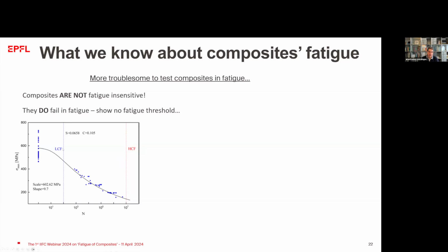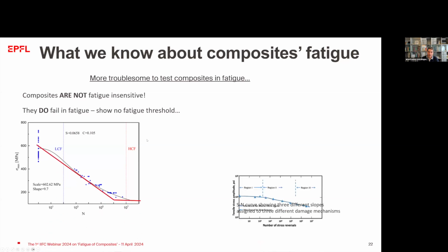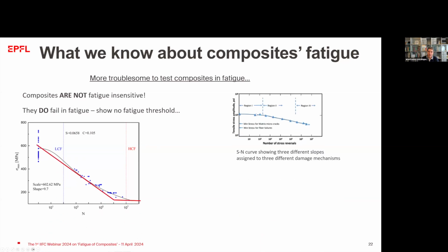In this curve also we can see 3 different regions of fatigue life: region 1, 2, and 3. Each one is related to different failure modes, and that's why we see experimentally that the curve has 3 different slopes. One big slope in the beginning, a more or less straight line in the middle, and then again a slope that is leveling at the end. And this is more or less what we observe for any composite material when tested under fatigue.